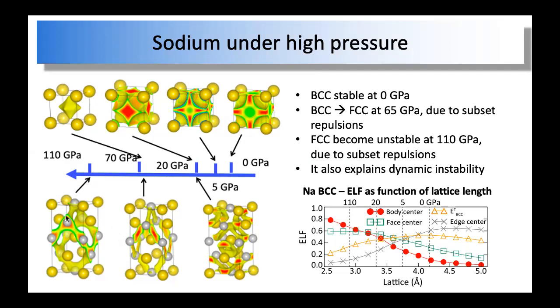So the ELF values shown here are calculated by the subsets shown by these yellow balls, right? And these white balls are the other subsets, and they locate exactly at the maximum of the ELF. That means they locate exactly at the electron localization point of the other subset. So therefore, they have very strong subset repulsion. So that explains that. And it also explains the dynamic instability, because the reason that all these high symmetry structures become dynamically unstable is because the two sublattices or two subsets are repulsing each other. If you move the atoms away from that, you lower the energy, right? From that particular point, you lower the energy. So therefore, if you calculate the phonon, your phonon will have negative mode or imaginary mode, right? So imaginary frequency, right?